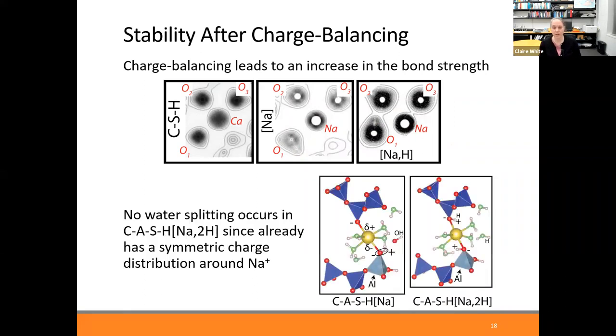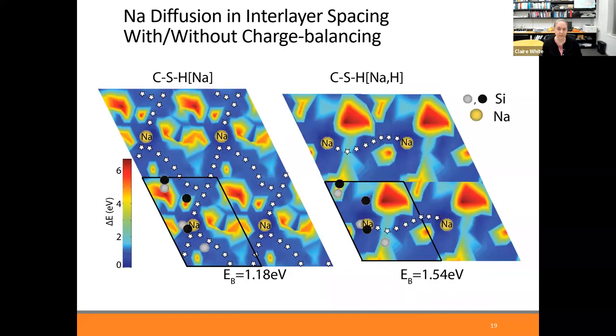We also saw what happened in this system without the hydrogen. If you've got a sodium in the system and you've also got aluminium in the bridging site, you don't have a symmetric charge distribution around the sodium. However, when you have charge balanced this structure, we do end up with a nice symmetric charge distribution around the sodium, which seems to enhance the stability of the structure.